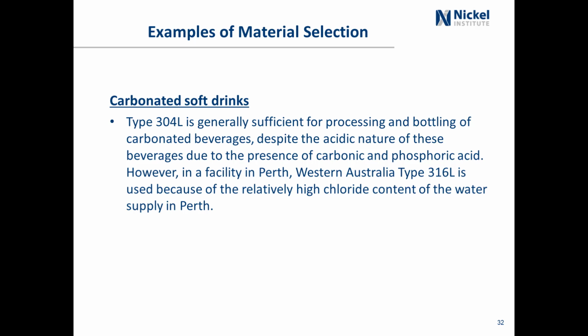And for carbonated soft drinks, generally type 304 is sufficient for processing and bottling carbonated beverages, even though the carbonated beverages have carbonic acid and phosphoric acid. At the concentrations that they're in a carbonated beverage, they are not a problem. But here's an instance in Perth, Australia. Type 316L is used because their water has a relatively high chloride content in it, and so they have to use 316L rather than 304.